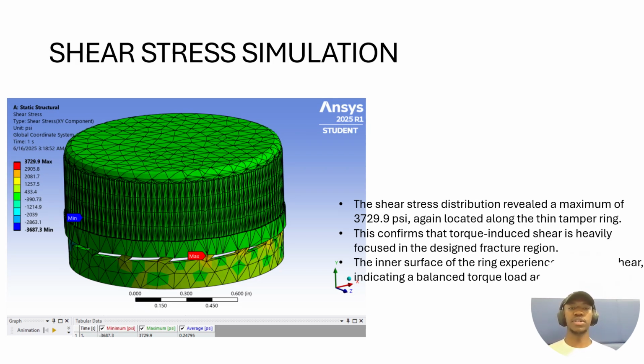And in this slide, you can see shear stress analysis, which revealed about a 3,700 maximum psi in shear stress that is located mainly at the notches here, and you can visibly see that red portion that says max. That's where the maximum shear occurs, and it occurs at the notches, which is good for our simulation because it justifies the whole point of the project.